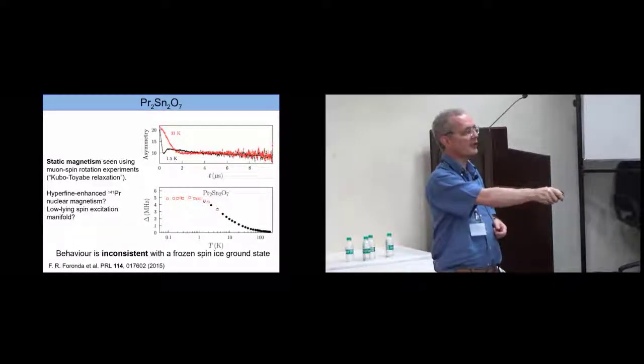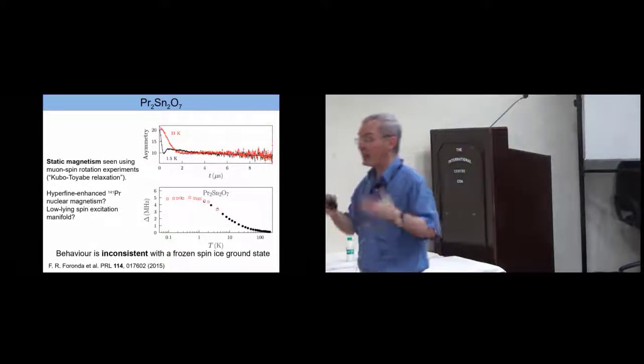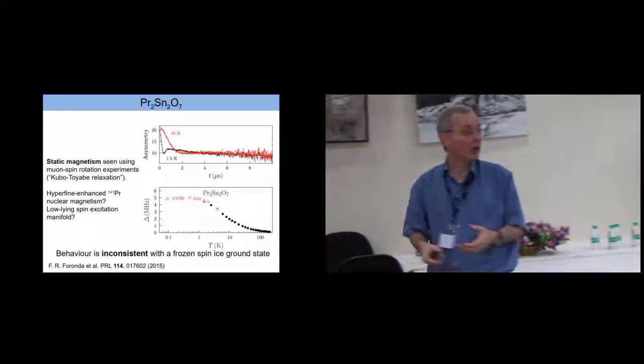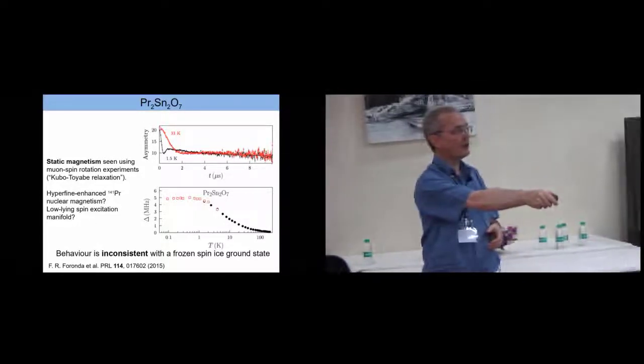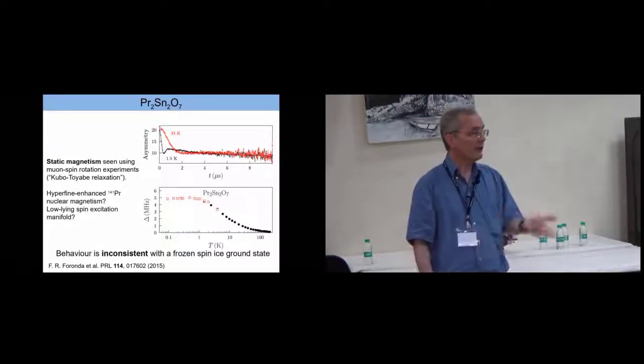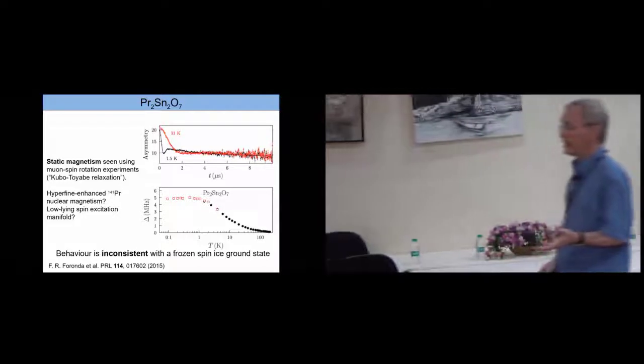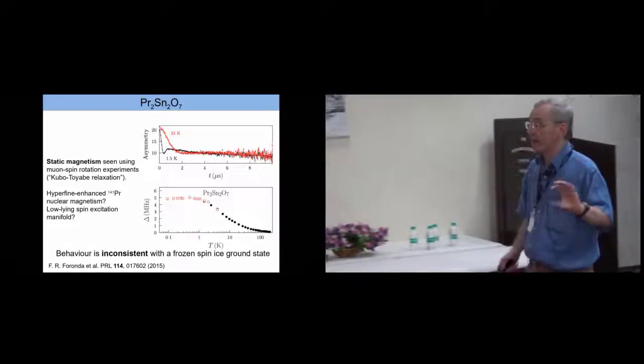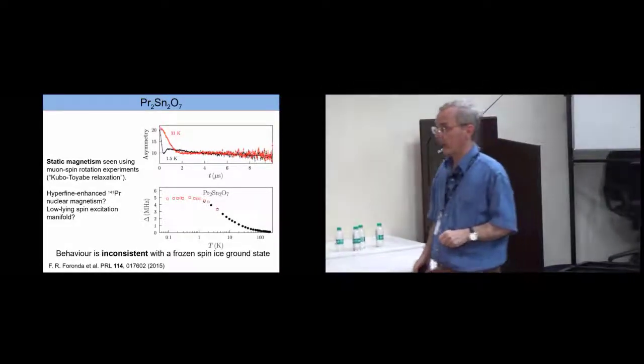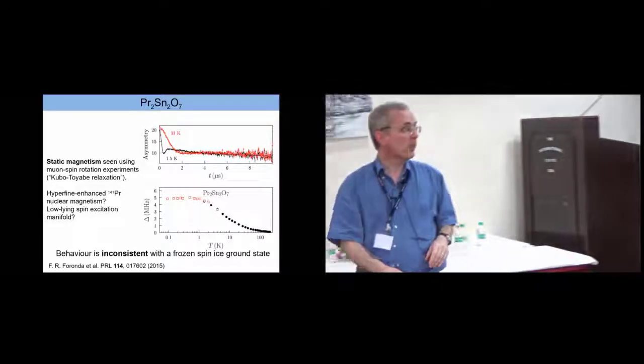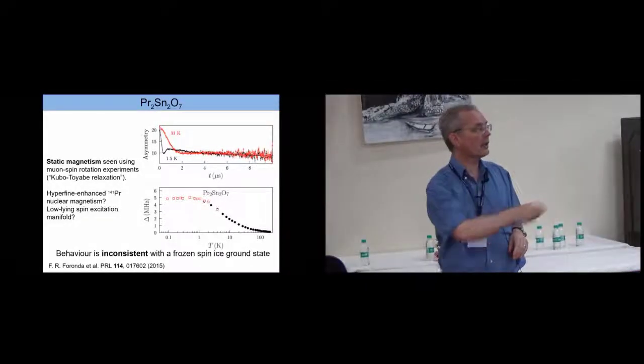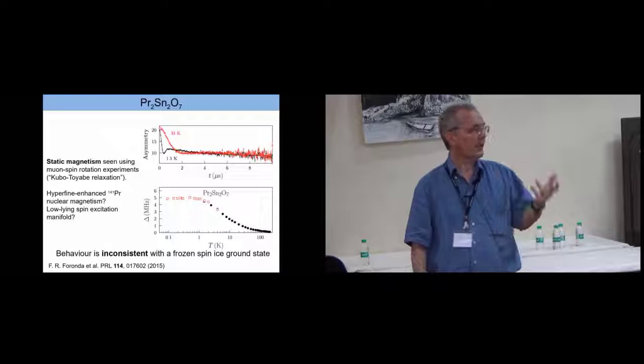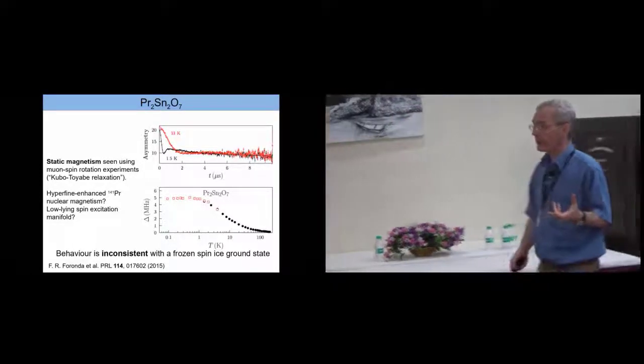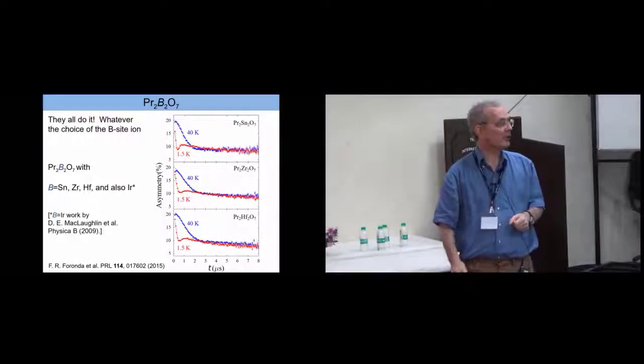And if you fit the so-called Kubo-Toyabe delta parameter, which tells you about the size of the internal field, essentially, it shows this very odd temperature dependence. Now, this behavior is inconsistent with a frozen spin ice ground state, even though other techniques say that you should have one. So this was worrying. What's more interesting is that the size of this delta is a bit too large to be a nuclear effect. So the whole thing looks puzzling.